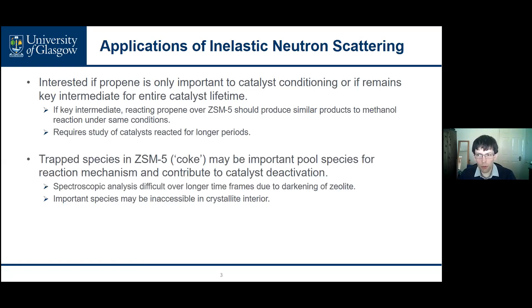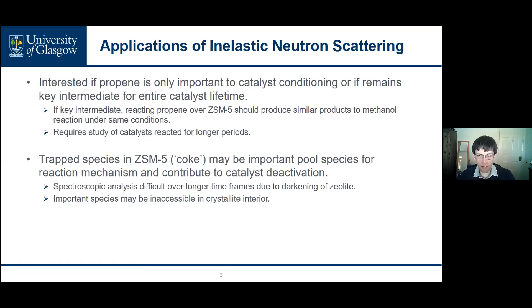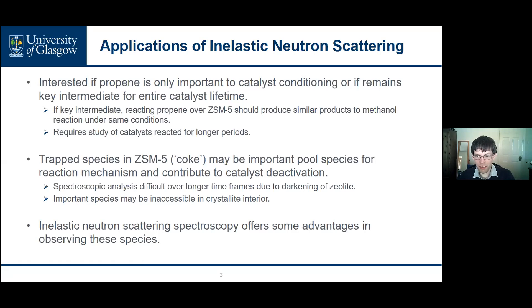This required studying the course of the reaction over a longer time period, which does lead to some issues with the build-up of coke species within the zeolite and darkening of the catalyst, which can make it difficult to observe the coke species by optical spectroscopic methods. Fortunately, we had already gained some experience in the use of inelastic neutron scattering spectroscopy, which has key advantages for examining these kinds of reactions over zeolites.